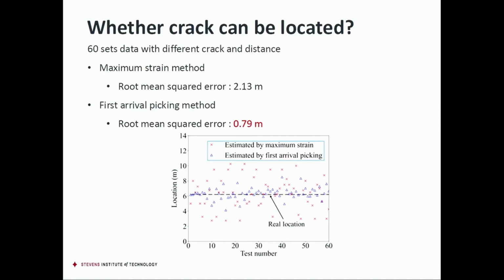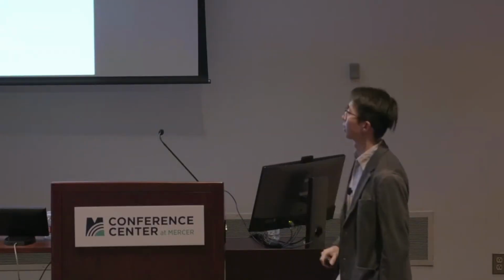The first one is the maximum strain method, and we found the results are not promising. So we proposed another method, which is the first arrival picking method. This method has already been widely used in acoustic emission and also ultrasonic testing. And we got promising results.